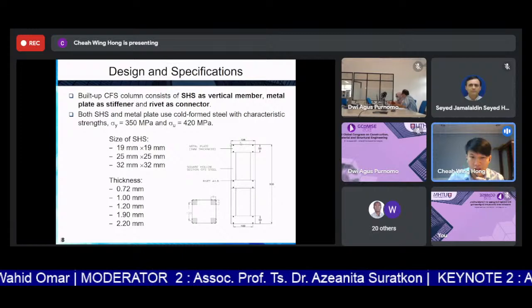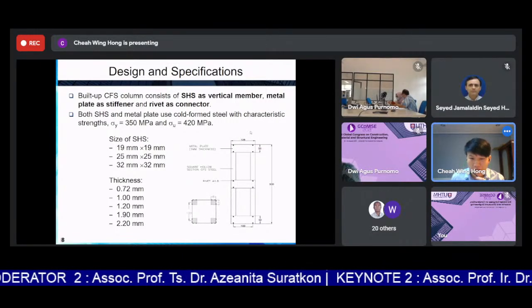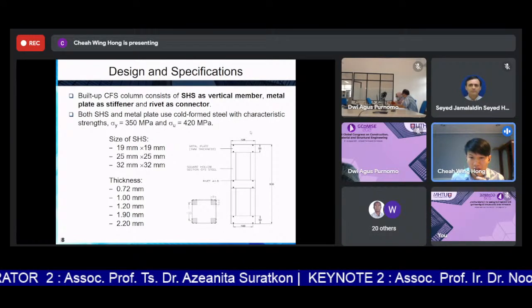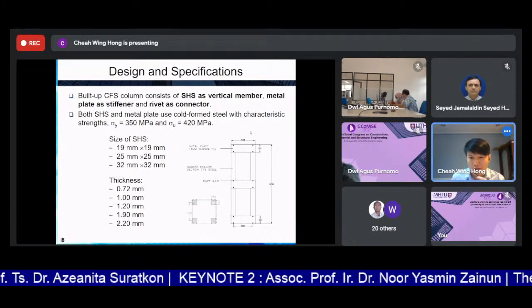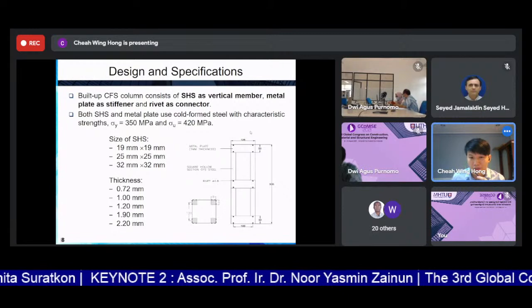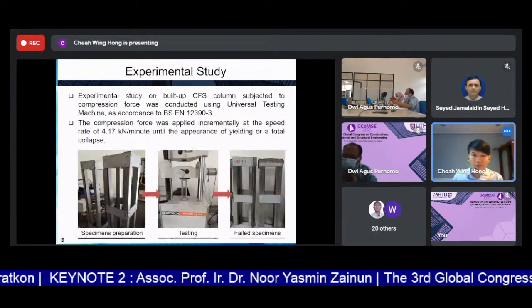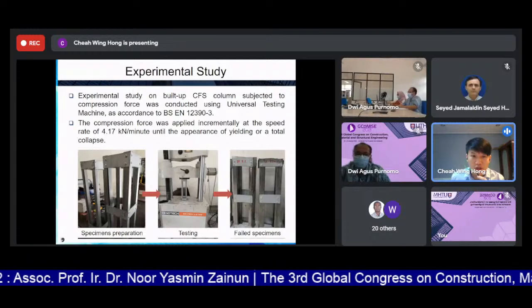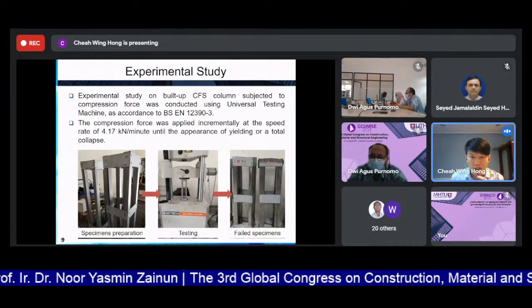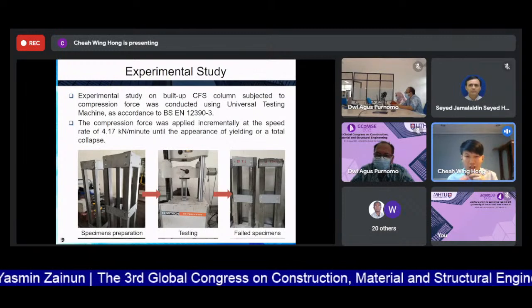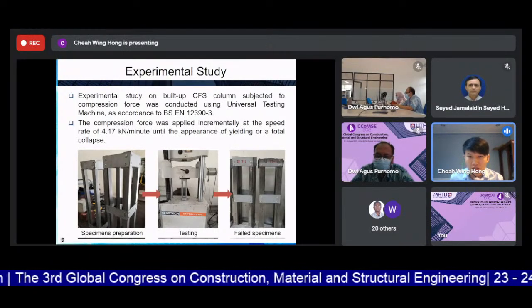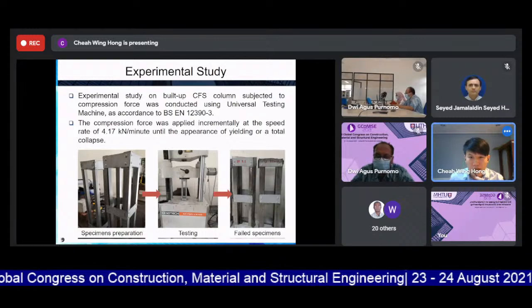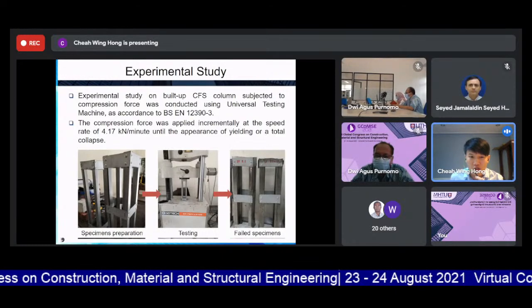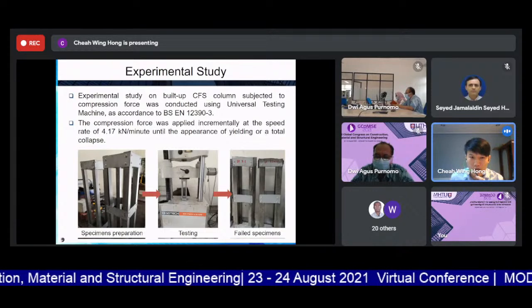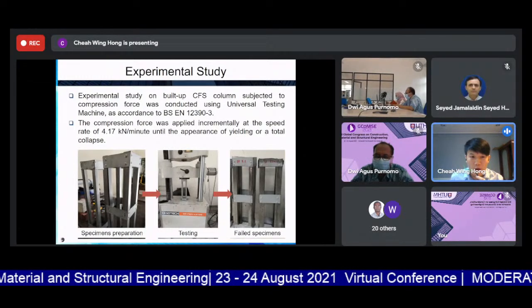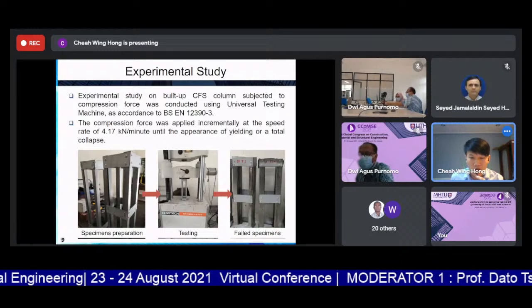And this is the schematic design of the CFS column. The length is about 125, and the metal plate thickness is about 1 mm. The numerical modeling is actually based on the previous experimental study conducted by a student in UTHM. The experimental study on the built-up CFS column was subjected to compression force and conducted using the universal testing machine. The compression force was applied incrementally at the speed rate of 4.17 kilonewton per minute until the appearance of yielding or total collapse.